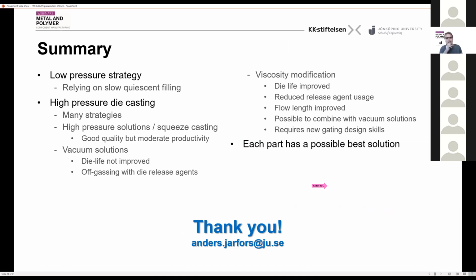So in general, I would like just to summarize this initial part, saying that if we look at low pressure strategies, the important part there is really to allow a slow quiescent filling. And that is by controlling either the actual pressure increase or the pressure difference between the die cavity and the furnace side. If you go to high pressure die casting, you have many more strategies. You have high pressure solutions, including squeeze casting. You get a very high quality of the casting, but again, you still suffer a bit in productivity because the squeeze casting process has a limited cycle time.